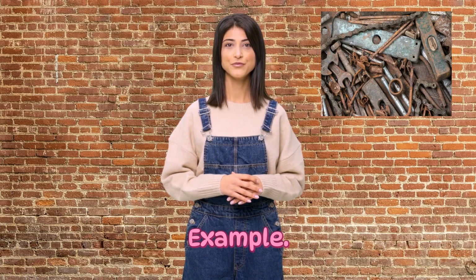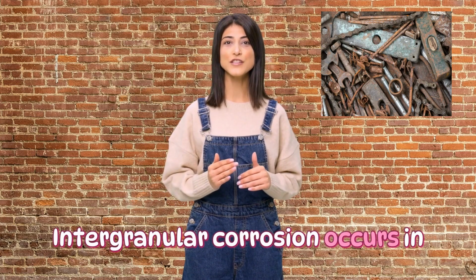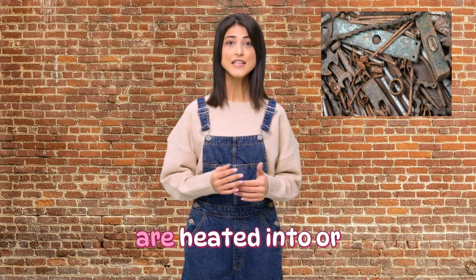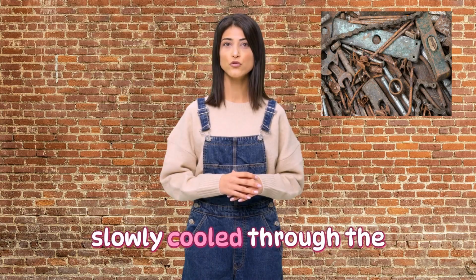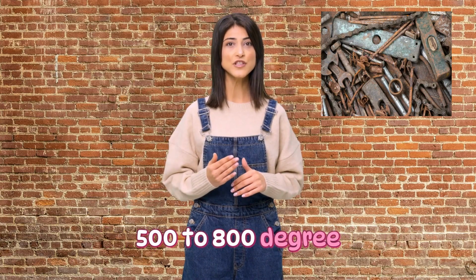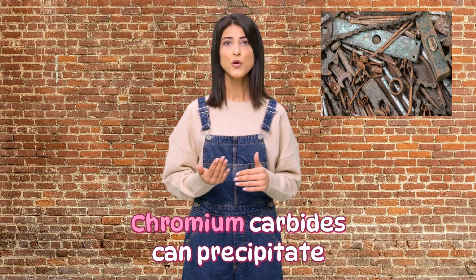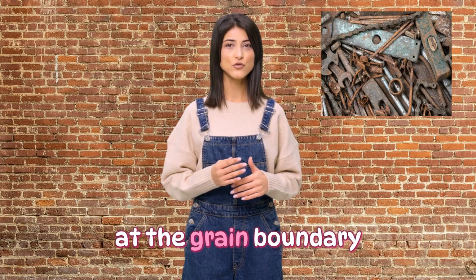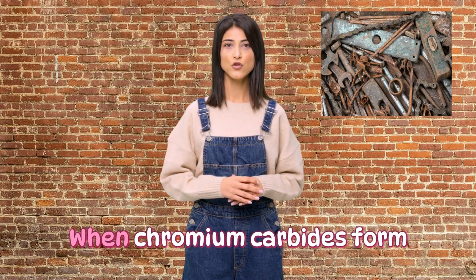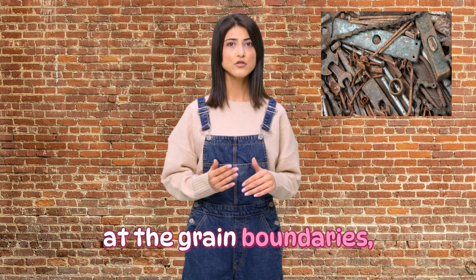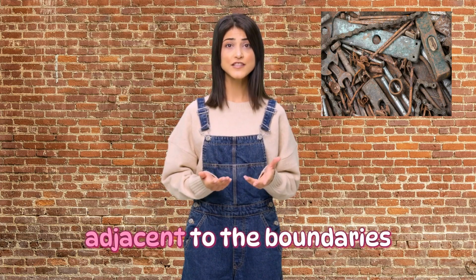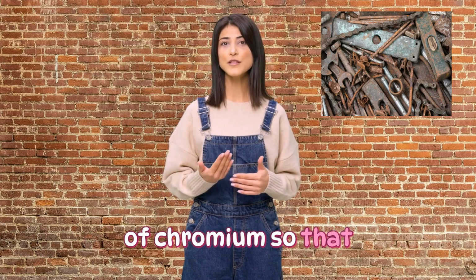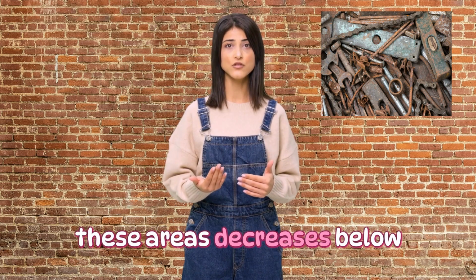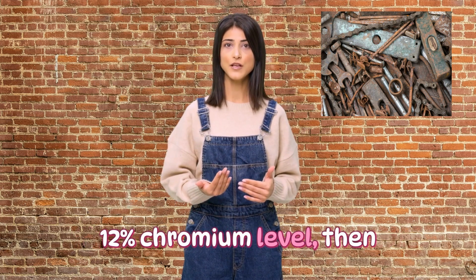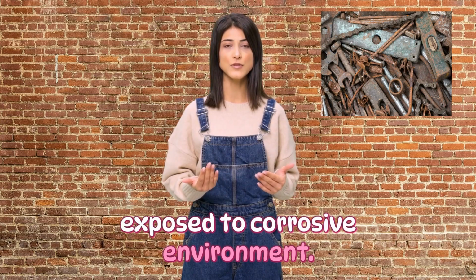Example. Intergranular corrosion occurs in austenitic stainless steel that is heated into or slowly cooled through the 500 to 800 degrees centigrade range. Chromium carbides can precipitate at the grain boundary interface. When chromium carbides form at the grain boundaries, they deplete the regions adjacent to the boundaries of chromium, so that the chromium level in these areas decreases below 12% chromium level, then exposed to corrosive environment.